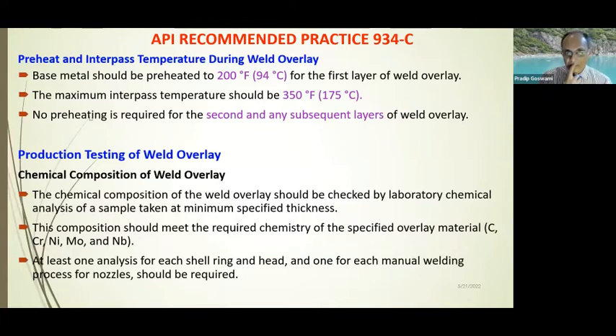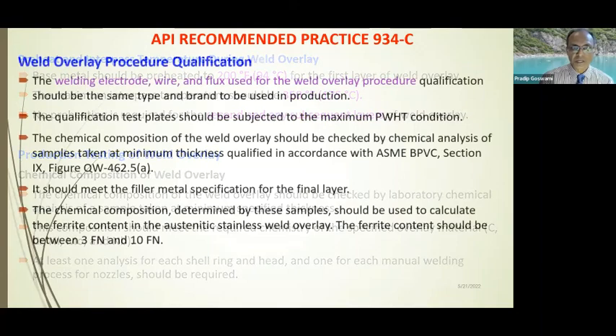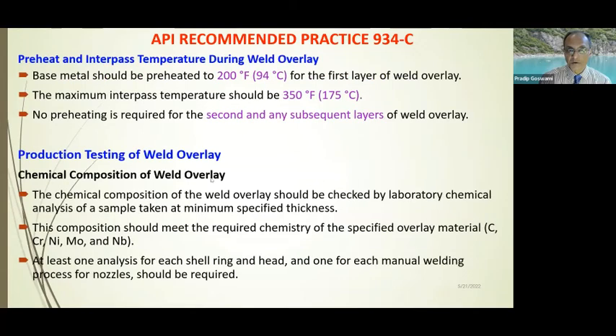Now, the earlier slide was on the weld overlay procedure qualification test. For the production welds also, one needs to have testing of the weld overlay, and it should involve a chemical composition check. The chemical composition definitely has to meet all the specified or required alloying elements like carbon, chromium, nickel, molybdenum, and niobium. This has to be taken at a number of locations, and basically one needs to take one location at each shell ring and head, every shell and every head, and one for each manual welding process for nozzles.